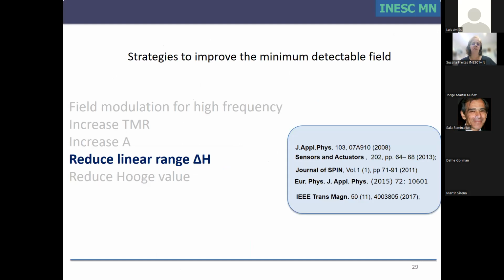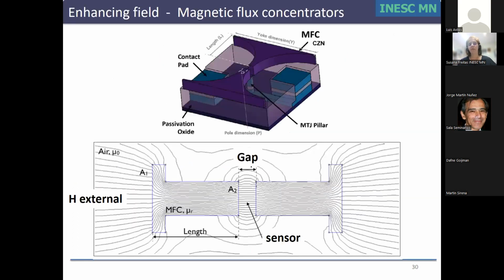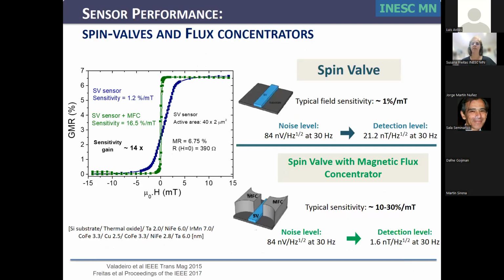Then an obvious strategy is to reduce the linear range, so to have more and more sensitive devices. Of course, we can think about adding flux concentrators. This is a strategy that is very old and very well known in industry, actually. If you want to enhance the field, you just have to focus the field that comes from the external media through very sensitive, high permeability magnetic materials. And then they will concentrate all the flux of this magnetic field into the region of the sensor. So this is a cross section here and a 3D vision. And the sensor is here in the middle, and we have the flux concentrators on top that help to enhance the magnetic field.